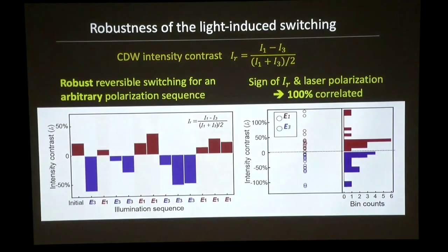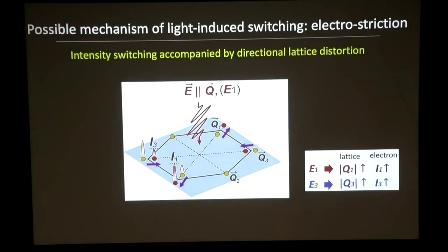So what does this mean? Well, first let me show you it's extremely robust. We have 100% fidelity, meaning if you shine light along some given direction, the charge density wave along that direction is going to get stronger, okay? So the question is, what could be happening? One hypothesis is that this is happening because the charge density wave is coupled very strongly to phonons and therefore to lattice distortion. And it's possible that the electric field of the light is shaking phonons along a given direction. And it's also actually causing something called electrostriction, meaning that the positions of the atoms themselves are actually changing due to the presence of light.